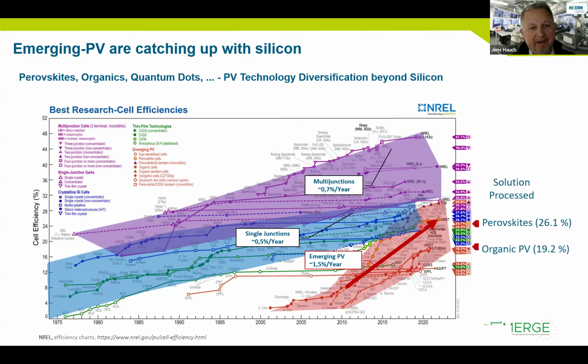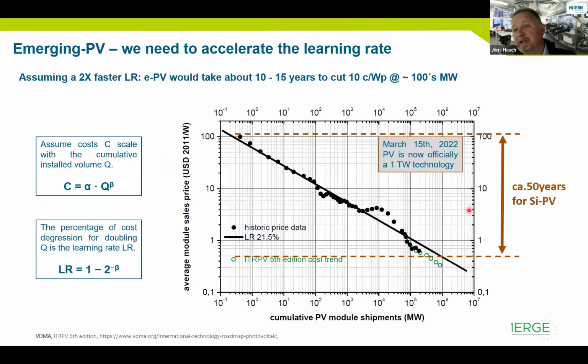My research group is actually very active in solution-processed materials in this range. So, disordered semiconductors that can be processed from solution, which is where the connection to emerging printed electronics is, of course. Let me just point out that the perovskite record right now is 26.1%, while the silicon record is at 27.6%. So we're getting quite close and overtaking things. But what I want to get at, or let me bring this back here.